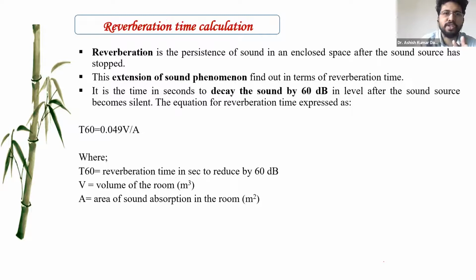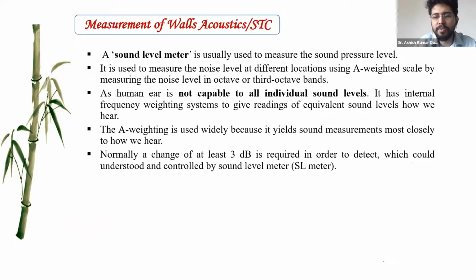And this is the reverberation time calculation. As we know, reverberation time is the decay of the sound. It is the time for the sound to decay by 60 decibels in level after the sound source becomes silent. So we also prepared the chamber of the concrete walls, both twin leaf system and single leaf system, to study the acoustic insulation.